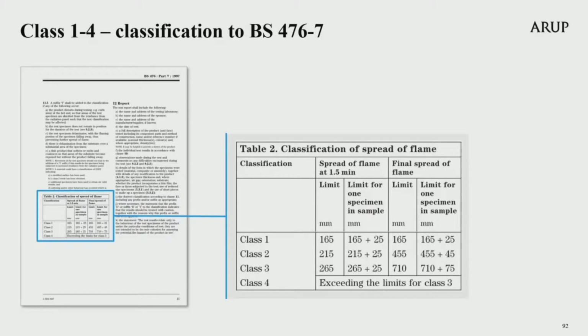This means the flame travels the least horizontally along the surface when a material is a class 1, and it travels the furthest along the surface on a class 4 material. The 1.5 minute measurement assesses the initial flaming, so how quickly the material reacts immediately after it is exposed to high temperatures. The final spread of flame, shown on the screen also, assesses how effectively the flame is sustained and can propagate along the surface. The flame spread must be within both limits set for a class to achieve that class.